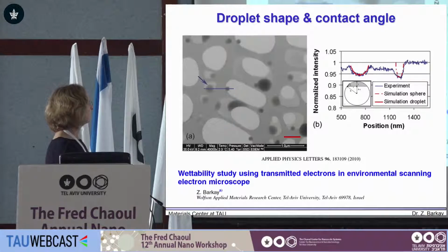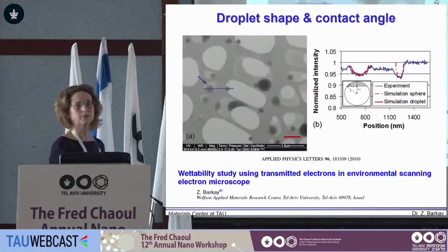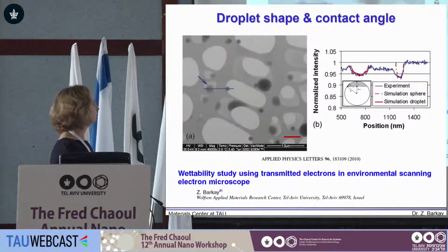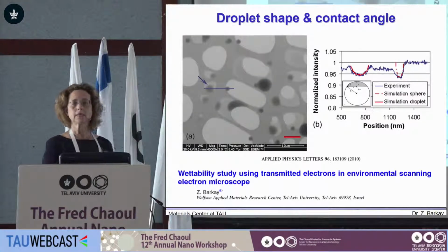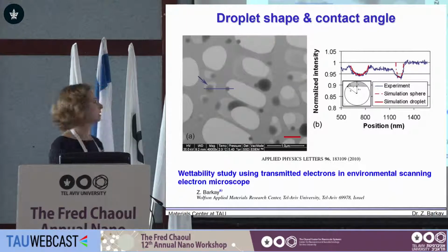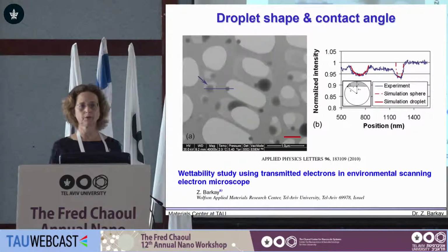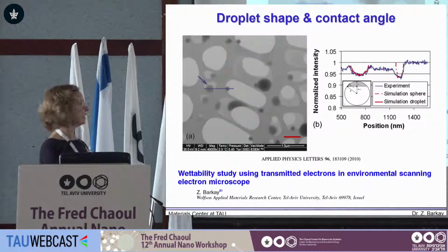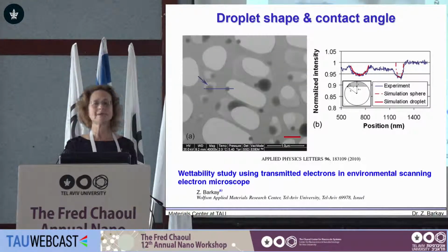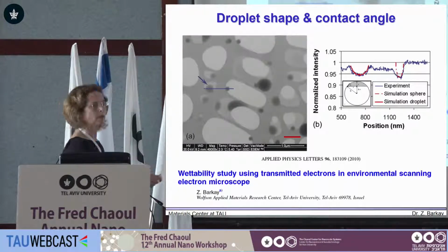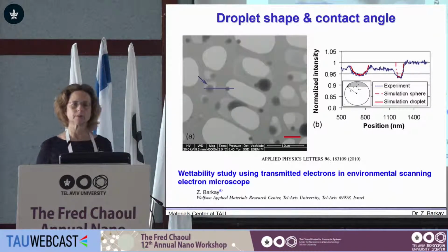Now, if we take a line scan across the drop and the polystyrene particle, we can get the normalized intensity after taking the calibration according to the polystyrene particle. This blue curve is normalized intensity, actually experimental intensity, normalized. From that, we can run a simulation to fit the curve for the drop and find the thickness. What we find out is that these are not spherical drops, but actually of spherical cap geometry.